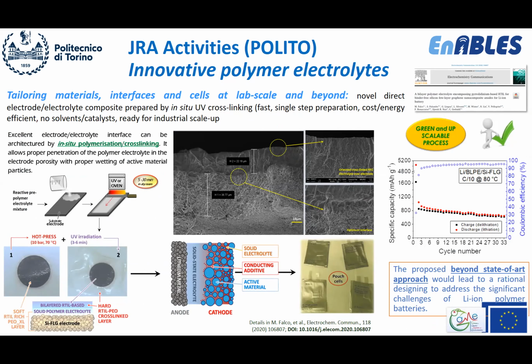On top of the performances of the material, what is very important also is to have a good interface between the electrodes and the electrolytes. Otherwise, some additional resistance can appear and be very detrimental to the good behavior of the battery. So what was achieved here was to develop an architecture with some in situ polymerization and cross-linking of the polymer.